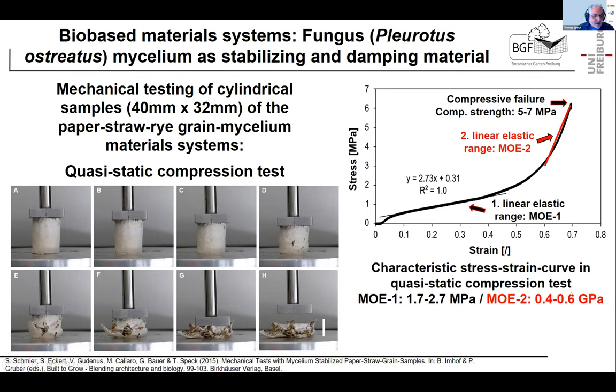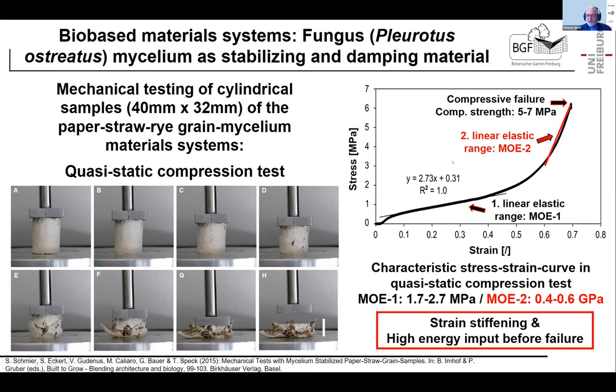And if you compare it, for example, to particle board, then this is about 10% of the modulus of elasticity of a typical particle board, and this is about a third of particle board. So it's not so bad. Even more impressive is the compressive failure. The compressive strength was between 5 and 7 megapascal, and this falls into the range of conventional particle boards, which range between 5 and 20 megapascal. What we see is strain stiffening, which is interesting, and a high energy input before failure, because you have this drastic deformation, which is possible before it finally fails.